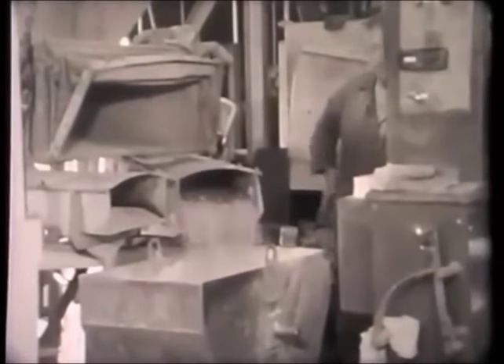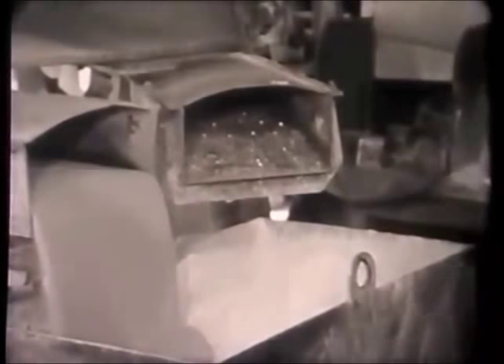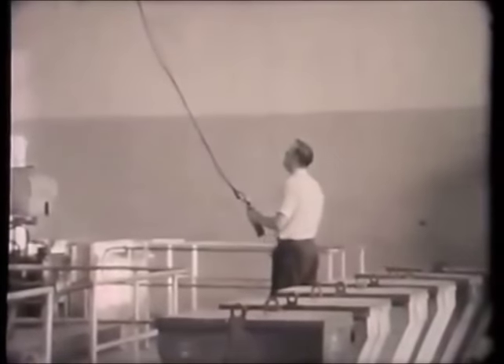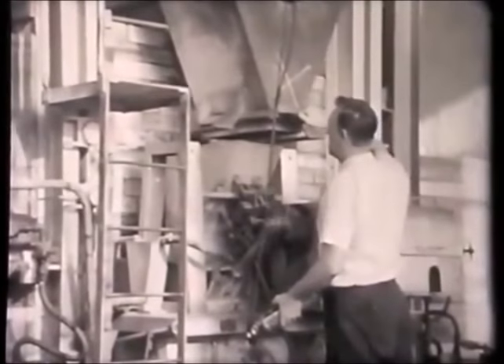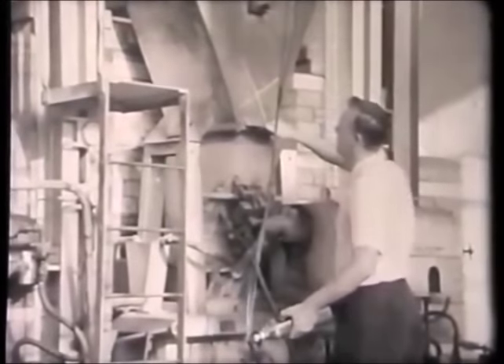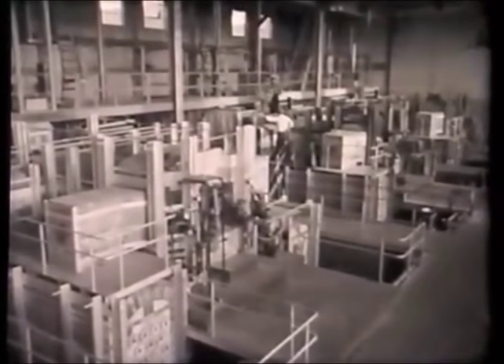Before leaving the process of base making, it may be interesting to see how the various parts of the base are made. First, the glass portion, which begins its life in the mixing room, where carefully weighed amounts of the raw materials are placed into a hopper. After the contents have been thoroughly mixed, the hopper is taken to the furnace room and placed in position on a melting tank. An automatic device gradually feeds the raw materials into the tank, which is heated to approximately 1400 degrees centigrade. Each furnace runs night and day for many months and only stops when a tank needs to be rebuilt.